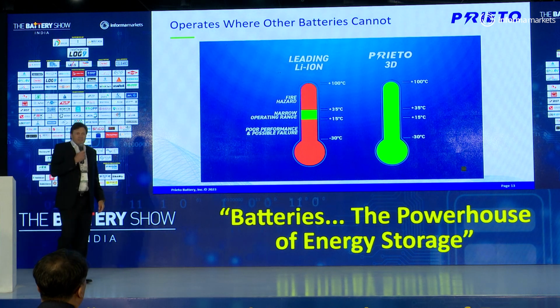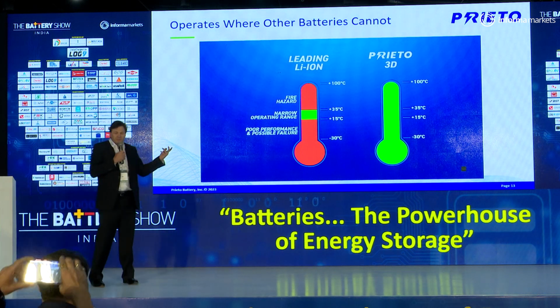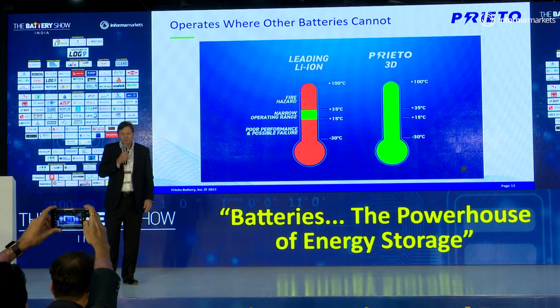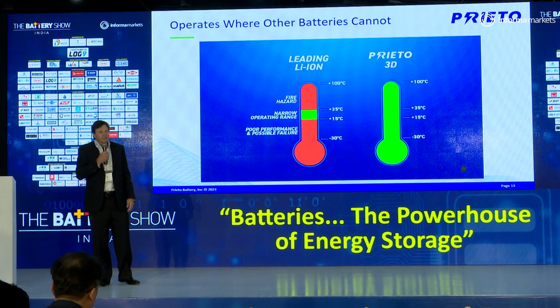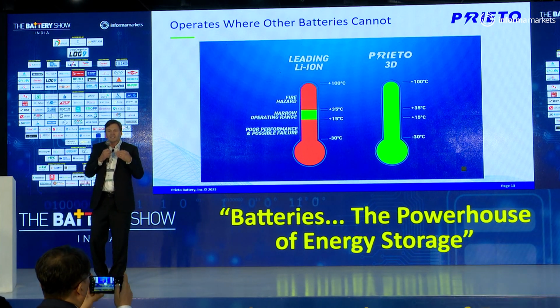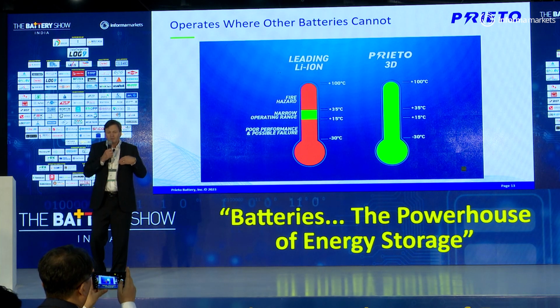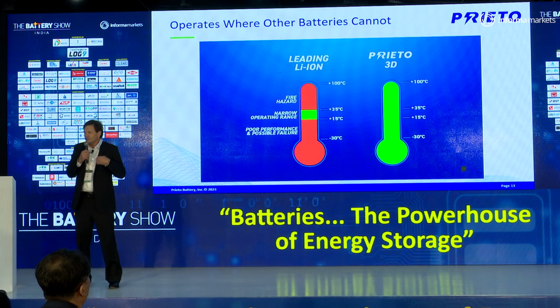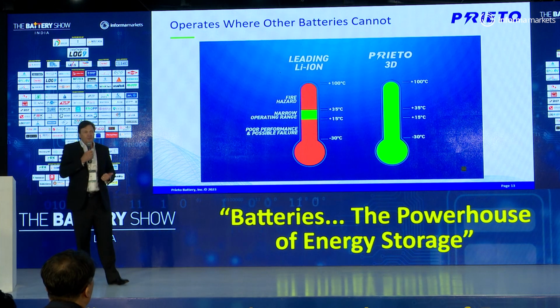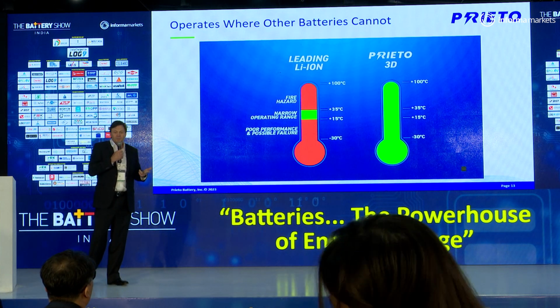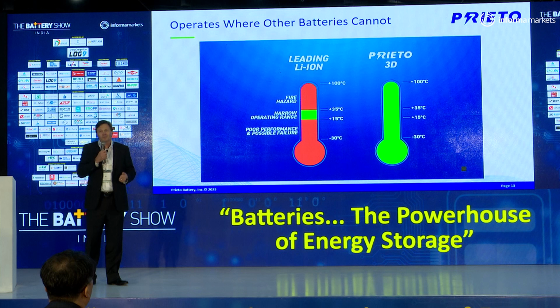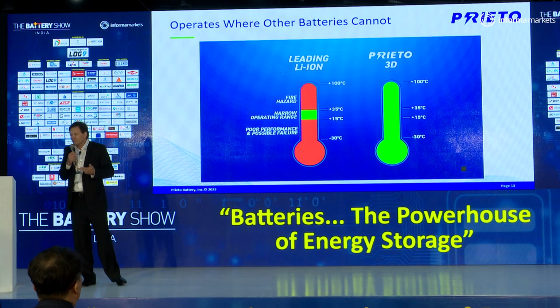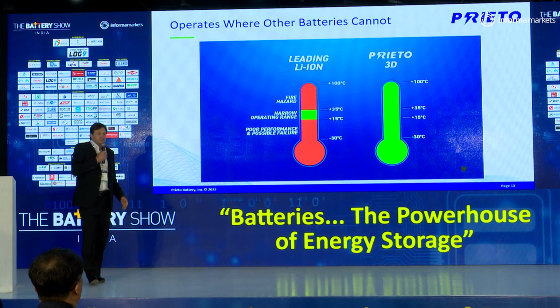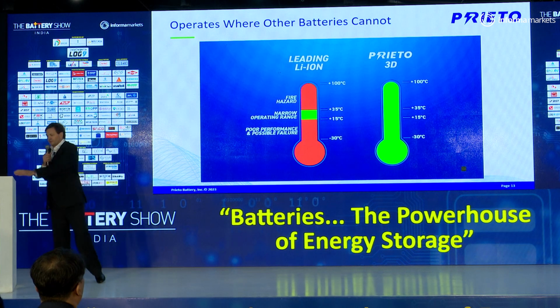From an operating perspective, traditional lithium-ion batteries have a very narrow operating window. It's typically between 15 and 35 degrees C. And if you get outside of those, if you get too far below that, you create damage to your cell, which then results in potential thermal runaway, fire, and explosion. If you run above that, you risk thermal runaway, fire, and explosion. Again, our battery operates comfortably between -30 and 100 degrees C.